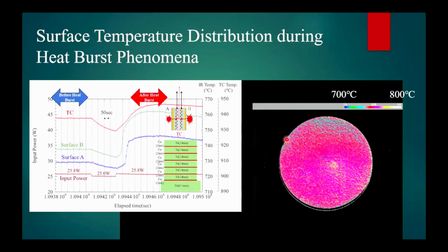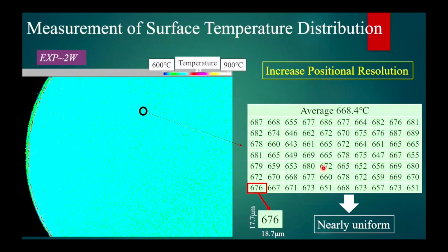Okay, and this is a demonstration of heat burst phenomena. Next we increase the positional resolution, and this data is a measurement of surface temperature distribution. In this case, excess heat is not so high, about 2 watts. And this is the raw data from the surface measurement system. One cell corresponds to 17 or 18 micrometers.